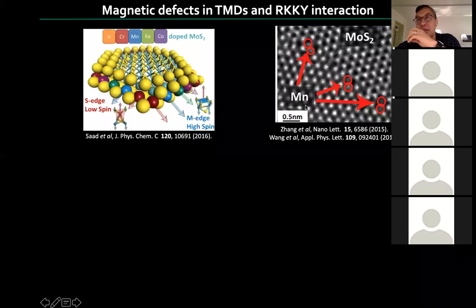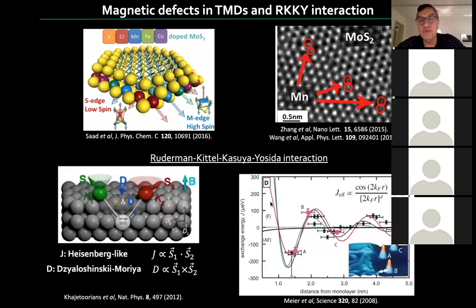You could also imagine scattering magnetic impurities on top of this, because after all, it's a surface, and so you can investigate with STM or whatnot. So what you would find is that if you put magnetic impurities on this material and ask, do they see each other? The answer is yes, they will interact because they have magnetic moments. Their dipolar interactions are direct, but that is relatively short range.